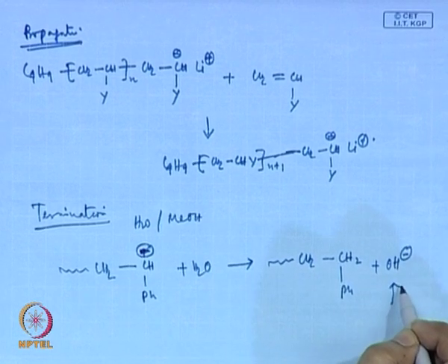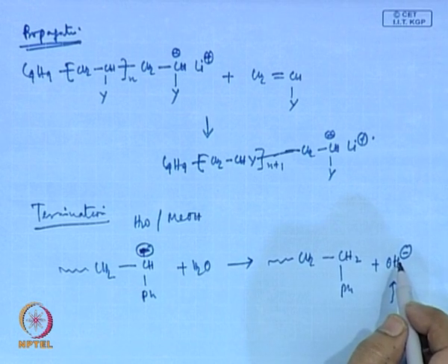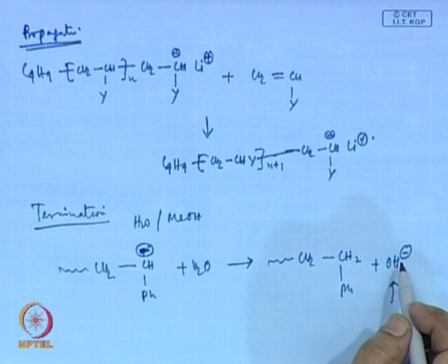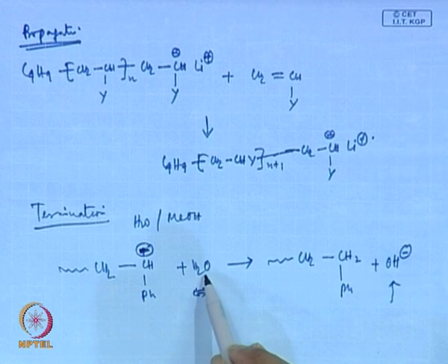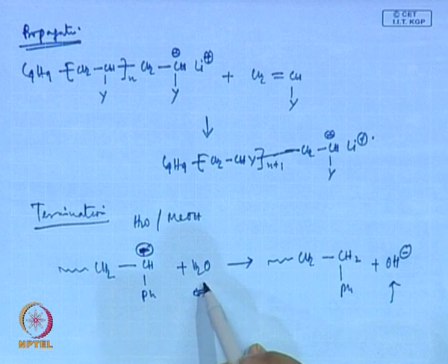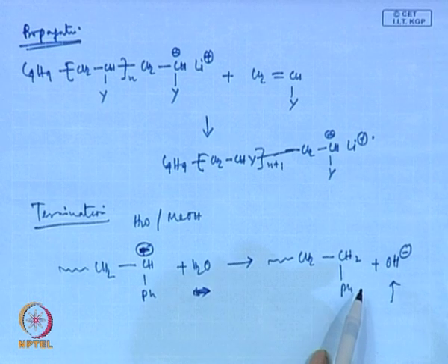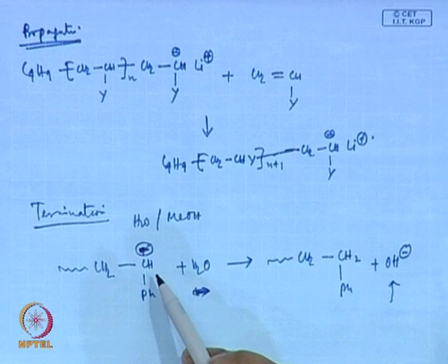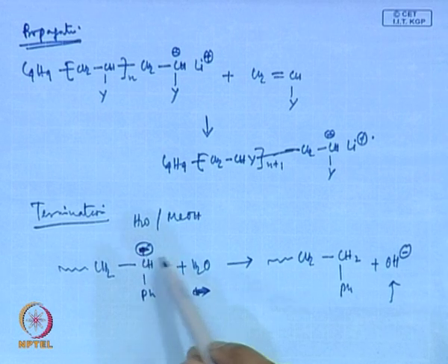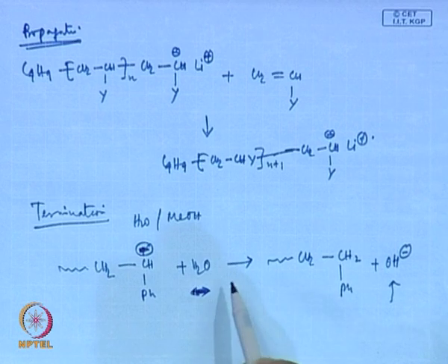Now, this is not sufficiently nucleophilic to reinitiate a chain polymerization, which also means that if you have undesired H2O present in the polymerization medium, it has a very detrimental effect in terms of molecular weight build up. Even trace amounts will immediately react with the propagating carbanionic end and stop the reaction, which is very detrimental for building molecular weight.